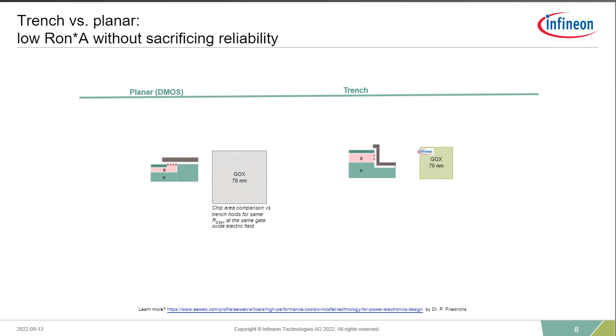So let's compare a little bit about the different structures of silicon carbide MOSFETs that are in the marketplace. On the left side here, you see a DMOS device, and on your right side, you see a trench-based device that Infineon is developing. One of the things you notice here is this 70 nanometer gate oxide thickness. This gate oxide thickness is standard of what you typically see in the marketplace for both an IGBT-based device or a silicon MOSFET. And this has a known reliability in terms of dielectric breakdown of the device, and is proven to have a very long lifetime in the application environment.